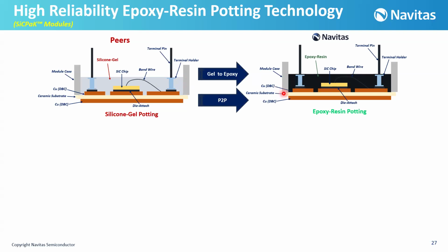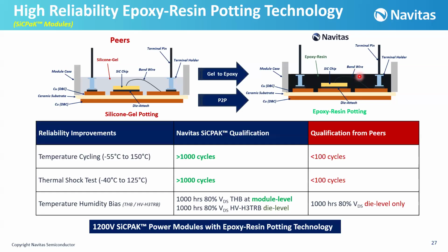So as a good apple-to-apple comparison, we compared our technology with this technology and just replaced the silicone gel with epoxy resin in order to have a fair comparison. So all parts are the same, and the only difference is just the epoxy resin. And here are the reliability results for both.